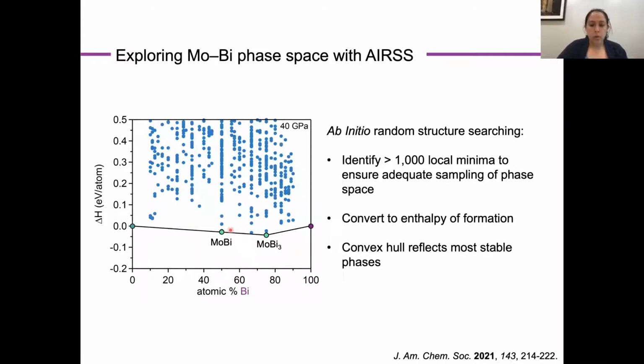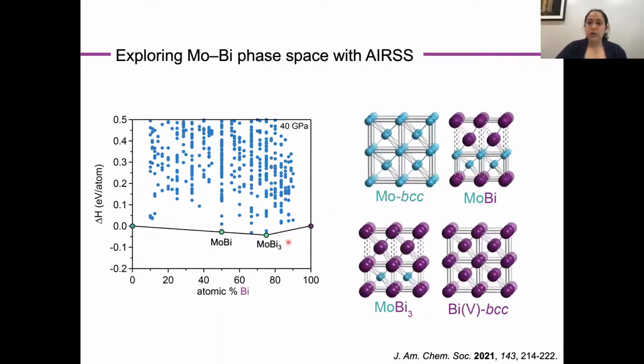We now have multiple structures which have negative formation enthalpies relative to the elements, including 2 structures, this 1-to-1 phase and 1-to-3 phase, highlighted in green, that now define the convex hull, suggesting that they're stable relative to each other. Examination of these structures reveals that they're actually quite similar both to each other as well as to the elements themselves. These are all based off this body-centered cubic, or BCC motif, in which you have a unit cell defined by atoms at the corner of a cube as well as 1 atom at the center. And in fact, this is a really common structural motif throughout this phase space.